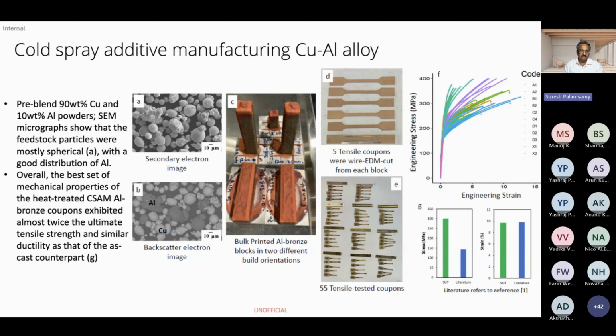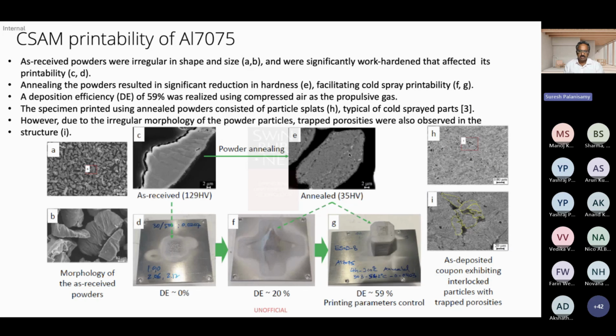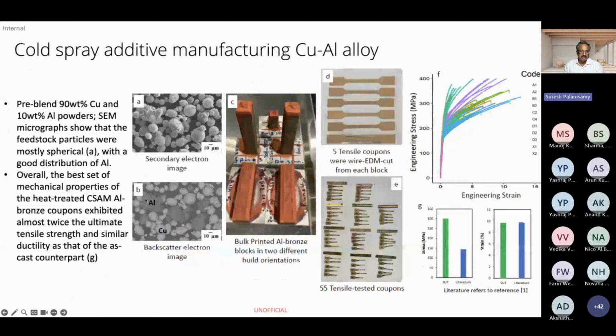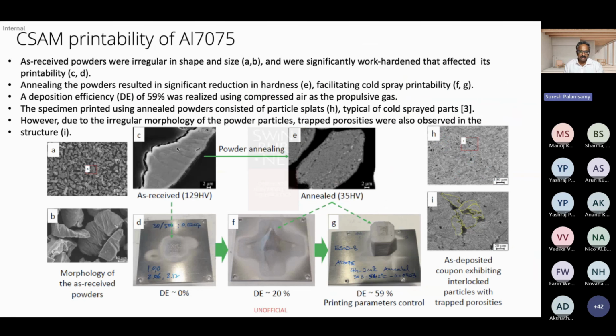This is what I talked about, the aluminum 7075 material, and how the particles look really different. This powder looks completely different to the powder particles you see here. Still, you are able to print the parts with the cold spray process. However, there is no way this can be done with SLM, because the powder particles cannot be pushed on the bed that easily.